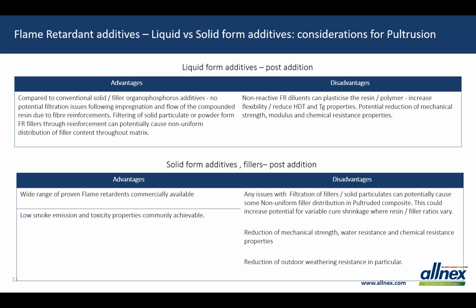We don't have increases in viscosity or filtration issues as well with the filler, which can cause a number of other problems. Some of these flame retardant additives can negatively affect critical flammability, processing, handling, and performance-related properties in the cured pultruded composite. So we typically need to modify the polymer or resin formulation with other materials to offset these effects, as I've mentioned.